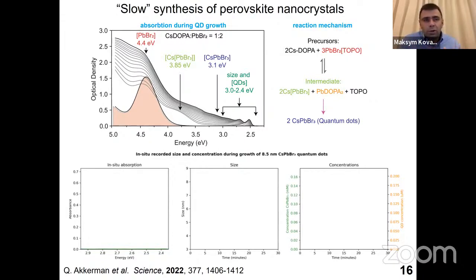And one way to accomplish that, and I believe there are many ways to accomplish this, but one is that, again, you don't use any amine. You use lead bromide and trioctyl phosphine oxide as a molecular adduct, which dissolves at room temperature in hexane, and you inject a cesium salt. So the only cesium in this synthesis is in the ionized form, more or less. The other precursor is fully molecular. And you see the absorption spectrum of this lead bromide TOPO adduct in the UV-vis spectrum.